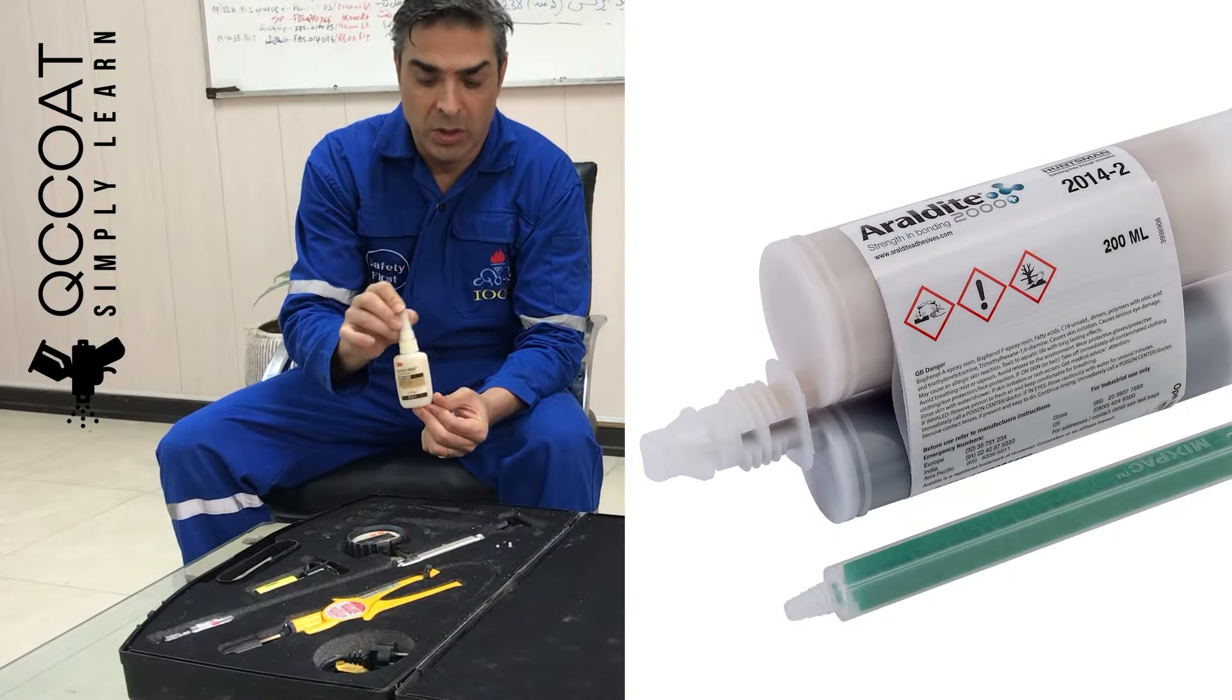According to the ASTM D 4541 standard, the following should be considered. There are five device models, the type of device is quite effective in the test results. At least three tests shall be done. 3.2 mm and 6.4 mm thickness shows different results. If the separation from the glue is more than 50%, the test is failed.